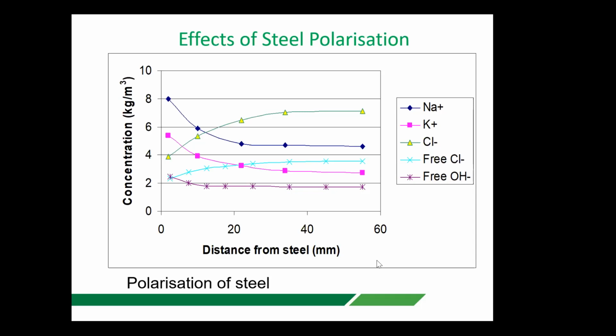This is perhaps a slightly exaggerated one. We had a current density of, I think, about 50 milliamps per meter squared. But you can see that demonstrates clearly what happens to the ionic concentration at the steel surface. This is the bulk of the concrete. This is the steel surface. And we can see that we are attracting sodium and potassium ions towards the steel. We are repelling the chloride ions away, and we are producing hydroxyl ions. The result is that you are increasing your sodium and potassium hydroxide concentrations around the steel reinforcement.